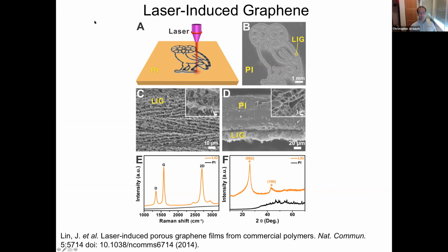In this picture, this was the original discovery made by Professor James Tour's group in 2014. And what we see is a laser hitting the surface. This is a polyimide polymer. And you can see this black coating formed on this substrate. And this black coating is a 3D porous carbon material full of graphene. You can see down here that it indeed is graphene. This is a Raman spectrum, which shows the 2D peak of graphene, the G and the D peak.